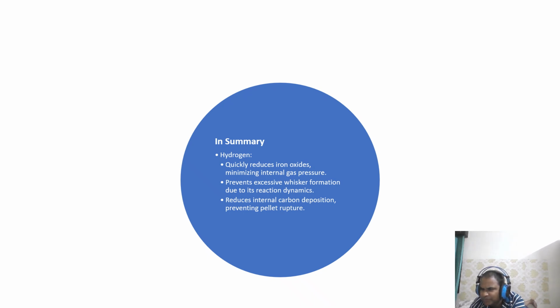So summing up, hydrogen benefits, let's wrap it up. Hydrogen reduces iron oxide quickly, cuts down on gas pressure, prevents excessive whisker formation and stops carbon from wrecking pellets. The result: stronger pellets, smoother operation and a brighter future for steelmaking. So hydrogen is the hero we need.